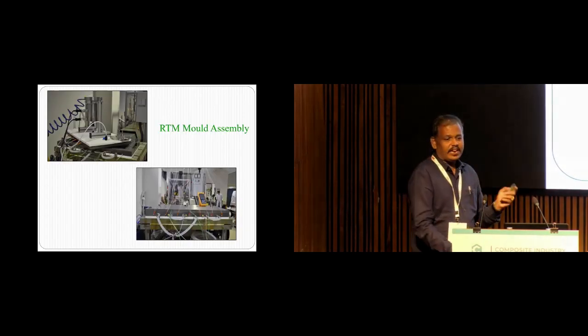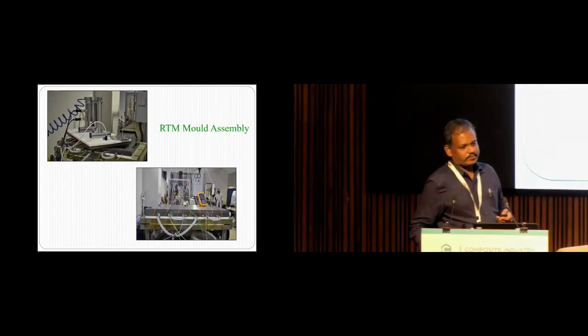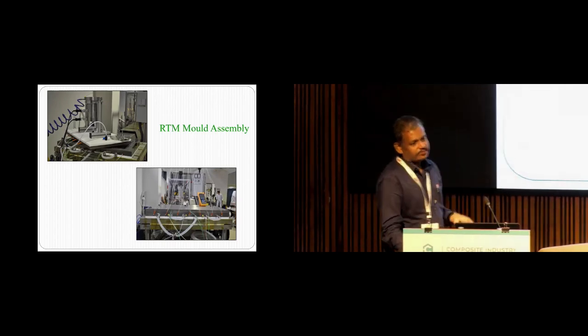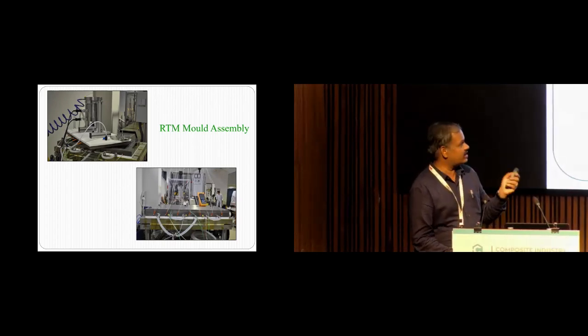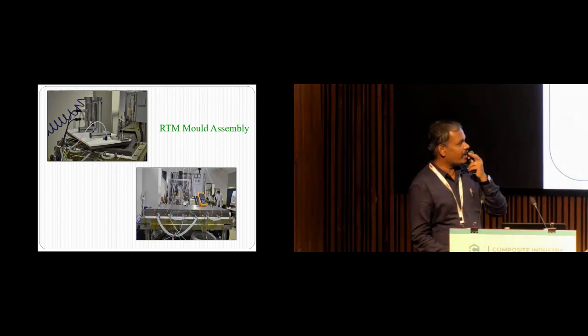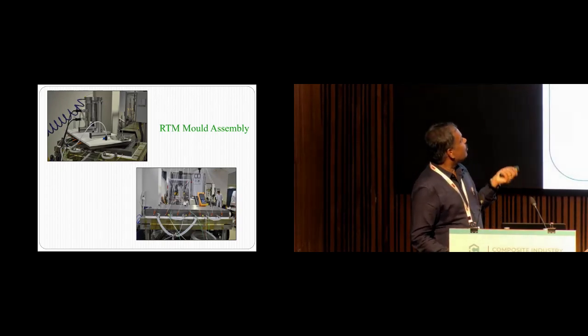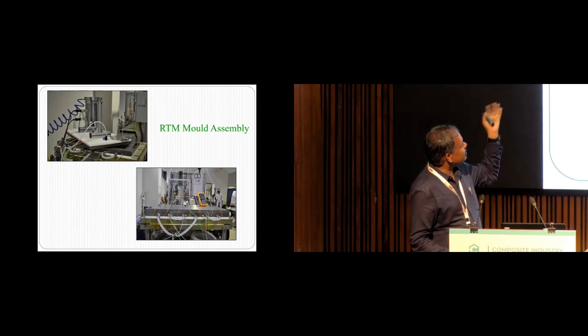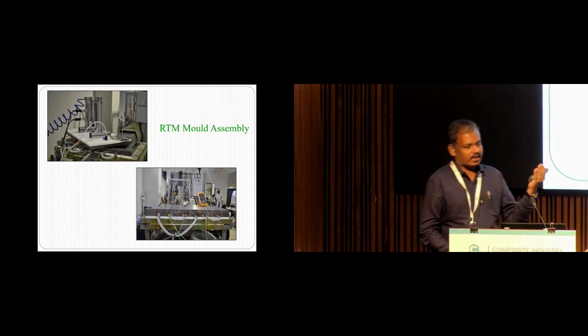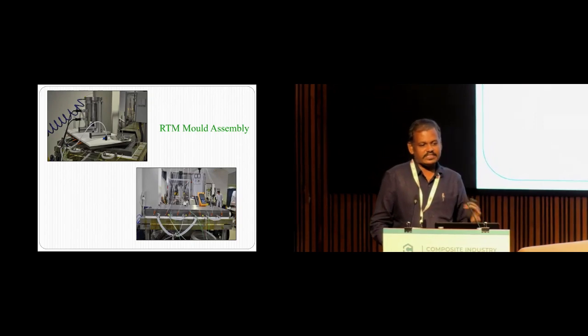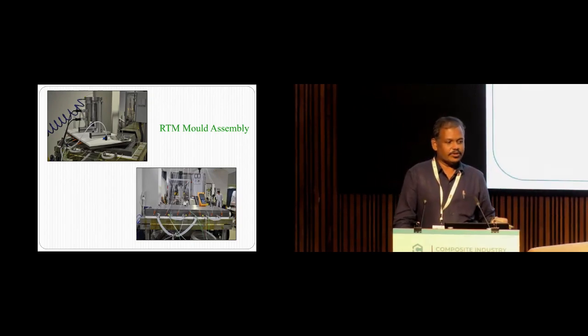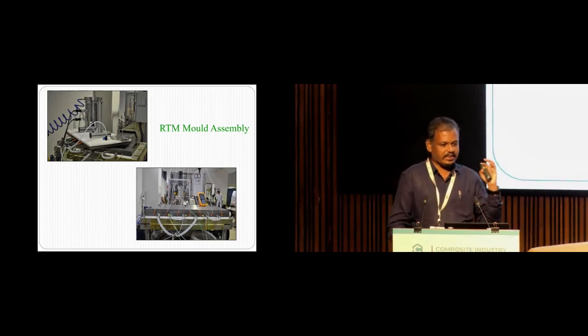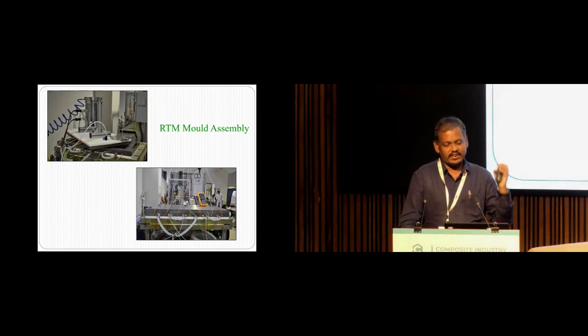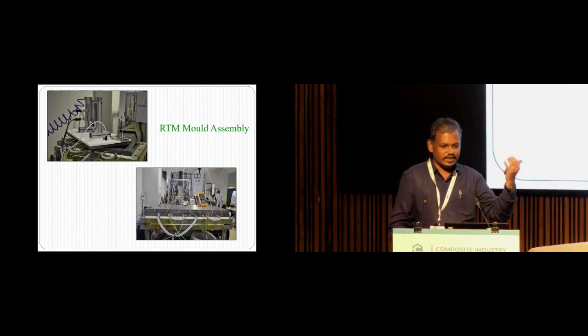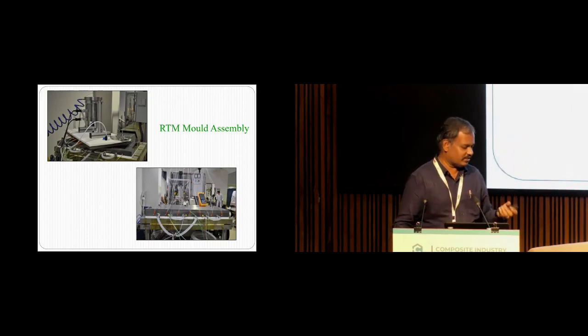Obviously we have tried out with the RTM also. This is not simply an RTM, this is vacuum enhanced resin transfer molding technology. This mold we have developed on our own. We have a resin tank also, because at room temperature RTM6 is a rigid solid, right? So you have to have a preheating temperature of 120 degrees centigrade. Before you inject the resin, you have to raise to 120 degrees centigrade so that the resin melts and it will have a flow consistency.